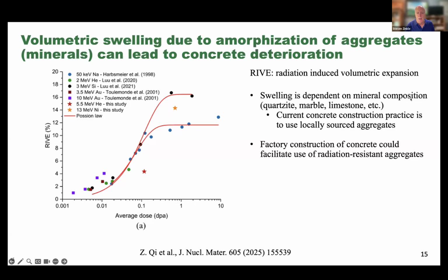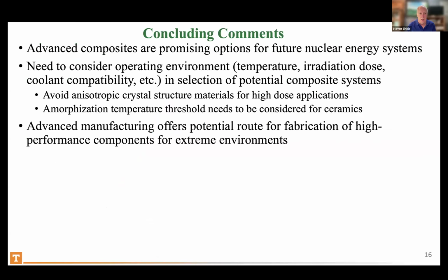This amount of swelling is dependent on the mineral composition. In particular, quartzite is relatively susceptible to this volumetric expansion. You can see 10 to 15% volumetric expansion in the case of quartzite, whereas marble or limestone are less susceptible to this volumetric expansion. And so if we look to the future of the possibility of factory build and then ship to site kind of construction methods, then you could use, rather than using locally sourced aggregates, which is the current standard practice, radiation-resistant aggregates such as limestone, etc., for the construction of the concrete that would be shipped to the site.